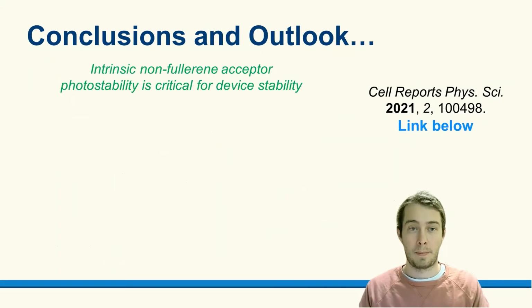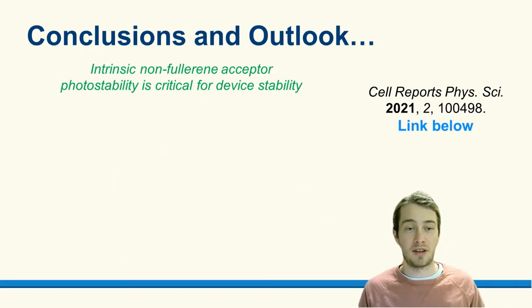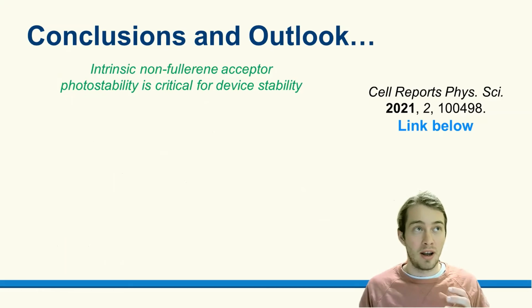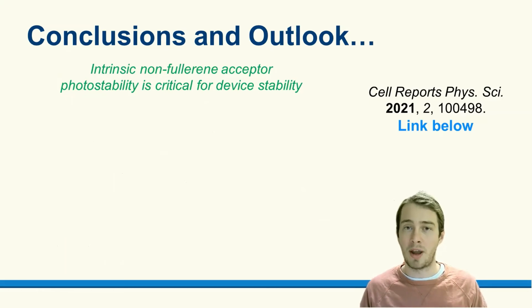And so, in conclusion, the intrinsic non-fullerene acceptor photostability is critical for device stability. So basically, the devices are degrading because ITIC is not very stable towards illumination. And if we were to stop this conformational change, or change these end groups, we may be able to make the material more stable and make more stable devices.